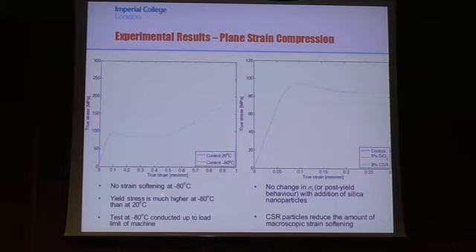When we go to minus 80 degrees, we see that this strain softening region has disappeared. Also, the yield stress is no longer defined as an upper yield stress, but the yield stress, 0.2% proof stress, is about 160 megapascals, so it's much higher than at 20 degrees. And this test here as well did not go to ultimate failure. We expected it to go on up here, but the load limit of the machine was reached when we got to about 260 megapascals. I did these tests in a 150 kilonewton machine.